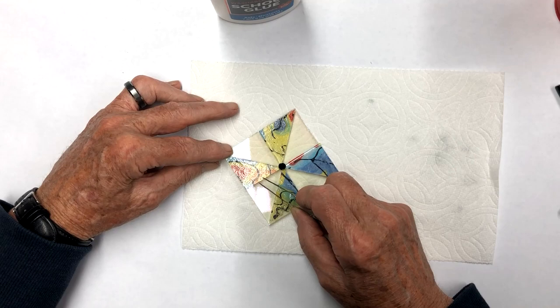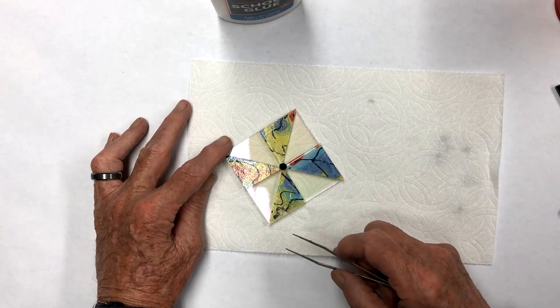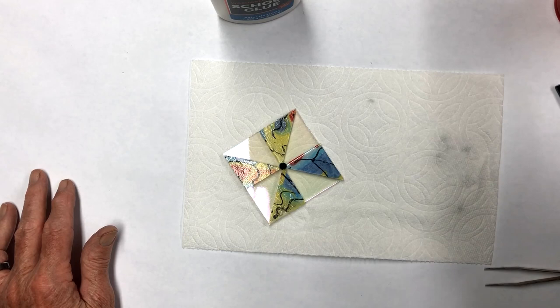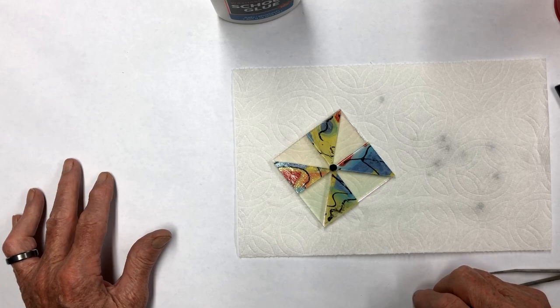Usually takes only about 5 or 6 minutes for it to dry. And then we'll be ready to put this in the kiln, and we'll go ahead and we'll fire it. And we'll do all the rest of them before, because we'll fire them all at one time. Going to fire this about 1440 degrees. I think it'll give us a nice contrast on our contour fuse. So you can see how all the different colors now change what we had made on our sheet.